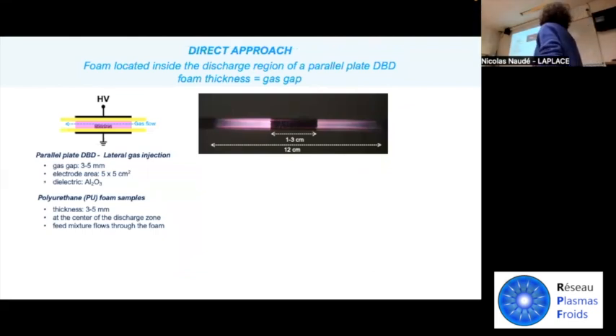The first approach we used is the direct approach. That is, we located the foam inside the discharge region of a parallel plate DBD system with lateral gas injection into the system. And we really sandwiched the foam between the dielectric covered electrodes of the DBD system, so that the feed mixture could be obliged to flow through the material.